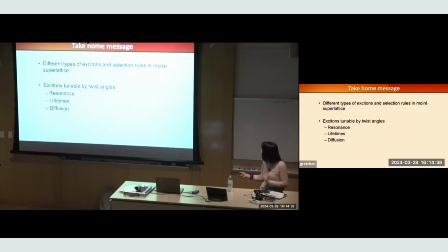So let me repeat the take-home message. I've shown you different types of excitons, intralayer and interlayer excitons. I showed you their selection rule is far more complex than a monolayer. I don't have that sigma plus to K valley, sigma minus to K' valley anymore. I may have a spatial pattern of selection rules. And the exciton properties, their energies, lifetime, and also the diffusion behavior can change with the twist angle. I skipped the diffusion; I don't have enough time to tell you about that.